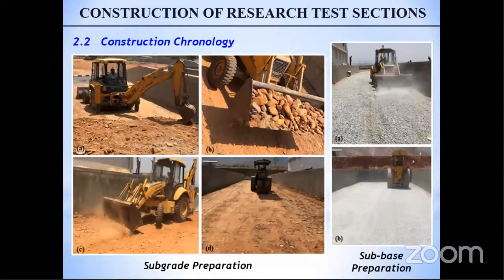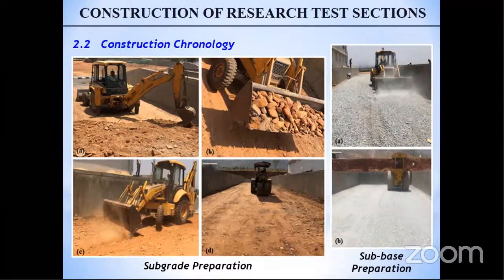So let's first talk about the construction chronology. We again excavated the existing substrate. A large amount of boulders, which are termed as excavated granulates, were removed from the site, because the presence of such large boulders will lead to the development of a poor substrate. So the first objective was to remove these granulates. Once that was done, good earth was laid and well compacted, which was followed by the laying of granular aggregates in order to prepare the subbase. Further, the subbase layer was compacted with the help of a static steel wheel roller.